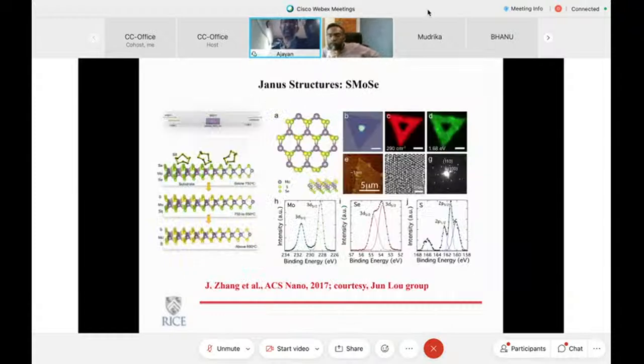There's also another possibility, which is in general called the Janus structures. So typically, as I said before, the molybdenum sulfide or tungsten sulfide, these dichalcogenides are in fact a three-layer unit where the metal atom is sitting in the middle, metal layer, and then sulfur on the top and bottom. But it's very easy to replace, for example, sulfur with selenium or another chalcogen or tellurium on one side. So you can get these completely Janus type of structures where one side is selenium, one side is sulfur, or vice versa. So people have, again, played around with this unique system where the single unit itself is kind of anisotropic because of the kind of chalcogen sitting on either side.